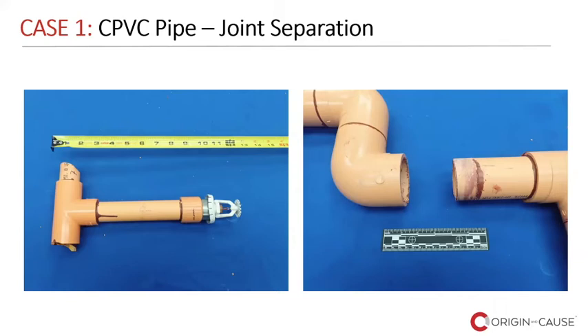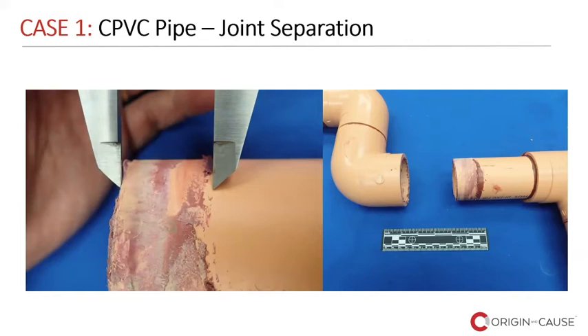There was also inadequate application of the contact cement. There was insufficient insertion depth, which is one of the most important steps, as there are several factors that play a role in the strength of the joint based on how deep it is inserted into the socket of the fitting. So I'm showing here in the picture on the left what we measured as the insertion depth, as well as how the contact cement was applied onto that pipe, and how it didn't make good contact on all the surfaces.